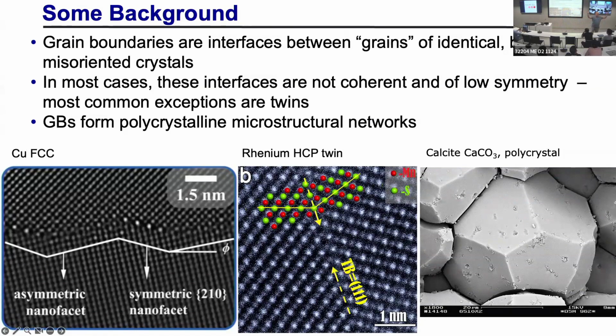Some crystals also have this on the macro scale. If you take something simple like salt, sodium chloride, of course these crystals are faceted, but this is faceted not on a macro scale, but on a nano scale. So we call this nanofaceting. In some materials, and this is just an example from rhenium, a hexagonal close-packed material, this is a very perfect twin. It's a mirror plane across here. So that's a boundary which is symmetric. Now, this last thing is a picture of calcite. And it's a three-dimensional grain structure. It happens to fracture very nicely, so you can actually see the grain structure fracturing along the grain boundaries.